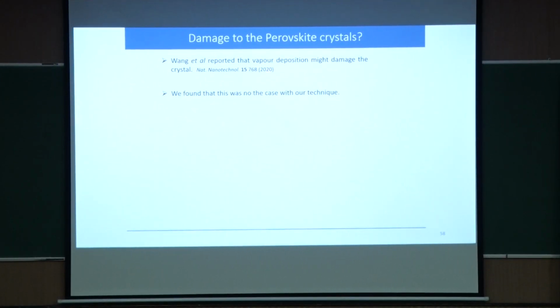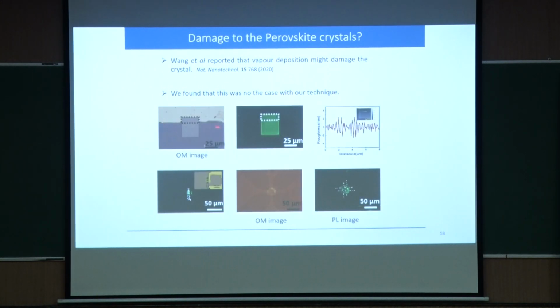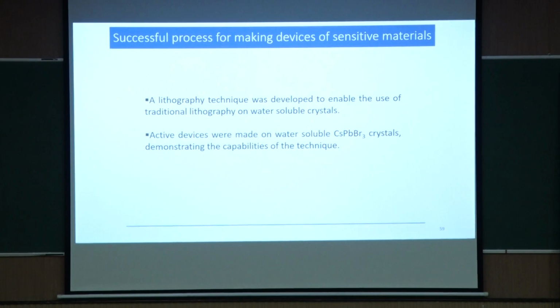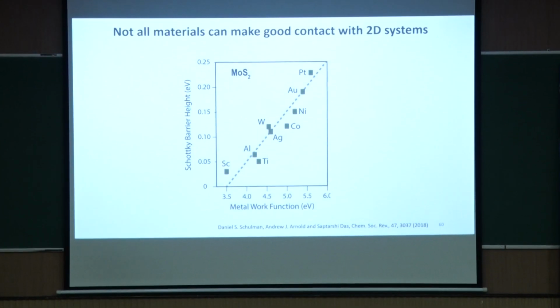But there is a report in 2020 where it claimed that this vapor deposition damages this crystal, but we found that it does not damage. So, what we did, we deposited metal everywhere, and then we sonicated to remove metal from this one, and you can see that the PL is intact. So, it really does not damage. We also did AFM, we found that there is no difference between the roughness in this side and that side. In this case also, after deposition, we sonicated and removed one electrode, and the PL is still intact. In this case, we made a transparent conductor, so even when the electrodes are there, you can see that the PL is intact, so it is not damaging. So, the sacrificial layer is successful.